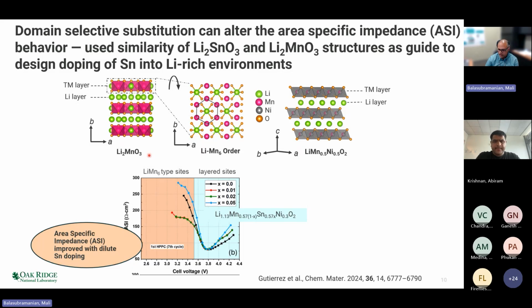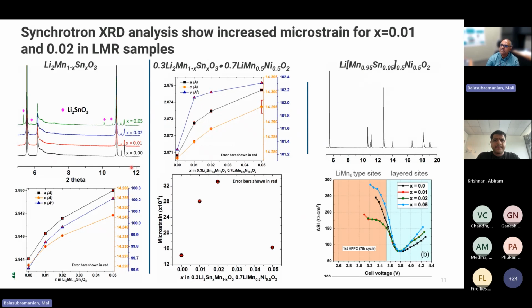Now, if you look at the X-ray diffraction, what you will find is that as the amount of dopant is increased from X equals 0.01 to 0.02 to 0.05, the solubility of tin goes down. That is, at a value of X equals 0.05, you start to see some of the tin come out as the Li2SnO3 phase. And you can also see that for the samples of the order of 0.01 or 0.02, there is increased microstrain, which you can see here in the XRD data. As you go to 0.05, the microstrain comes down again, so the microstrain is relieved when you start going to a large amount of tin dopant.